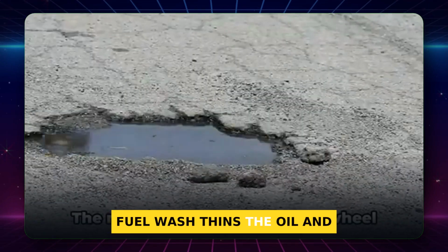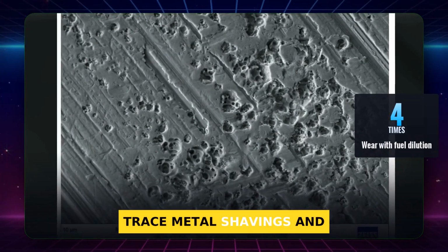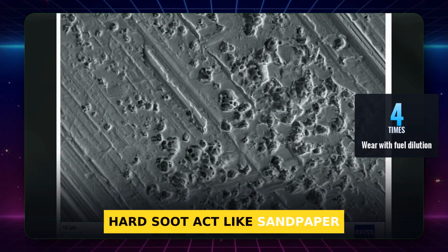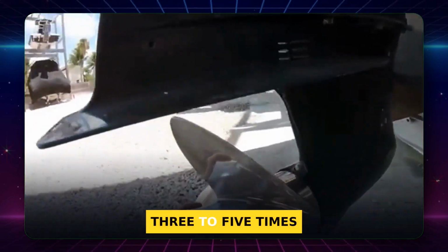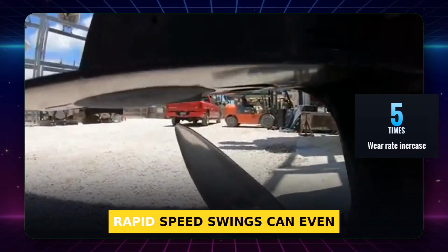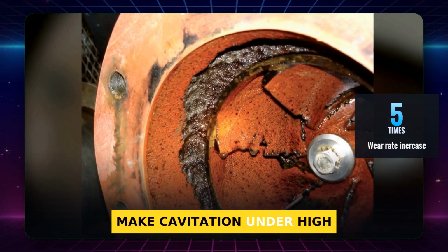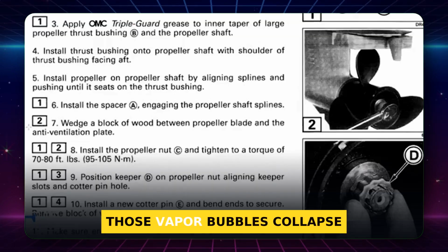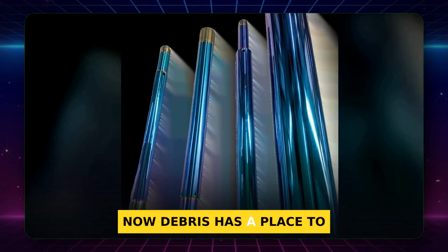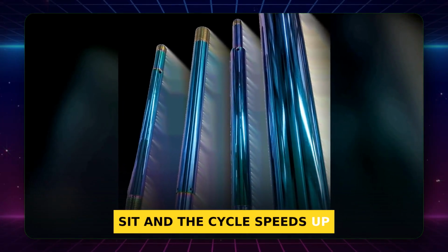Fuel wash thins the oil and can push wear to 4 times normal. Trace metal shavings and hard soot act like sandpaper and can boost the wear rate 3 to 5 times. Rapid speed swings can even make cavitation under high-load bearings. Those vapor bubbles collapse and pit the surface. Now debris has a place to sit, and the cycle speeds up.